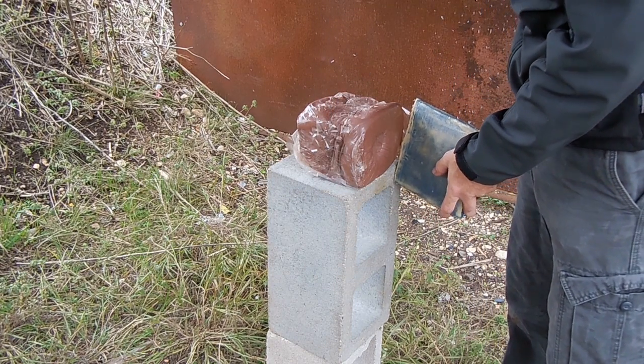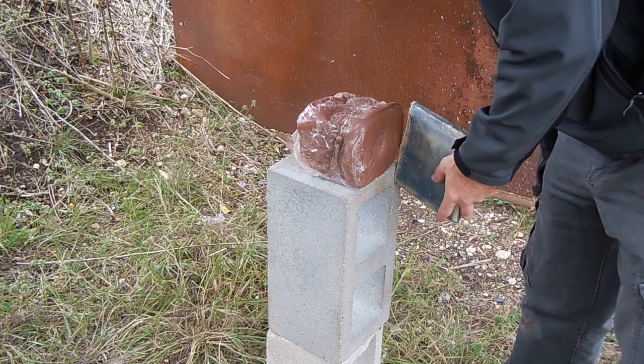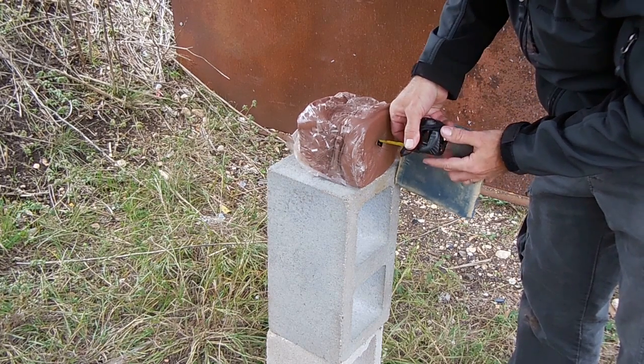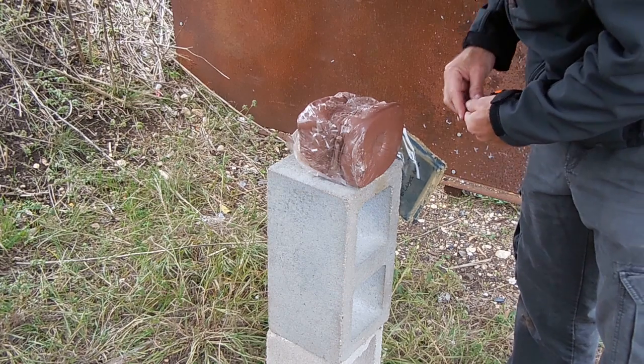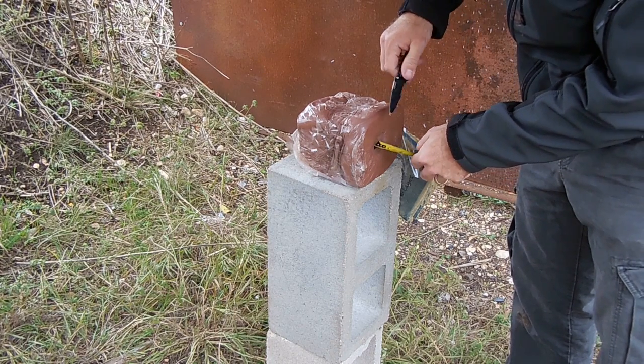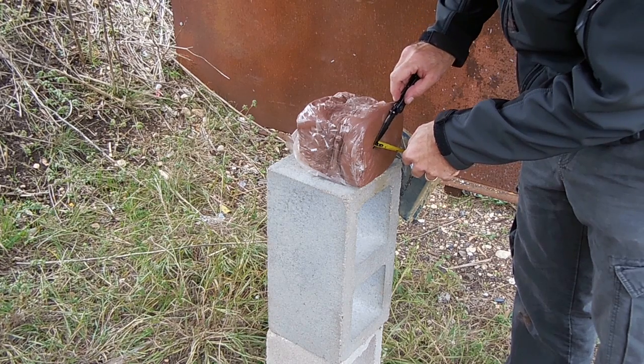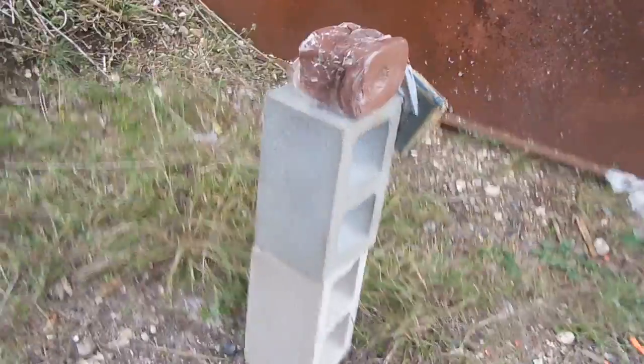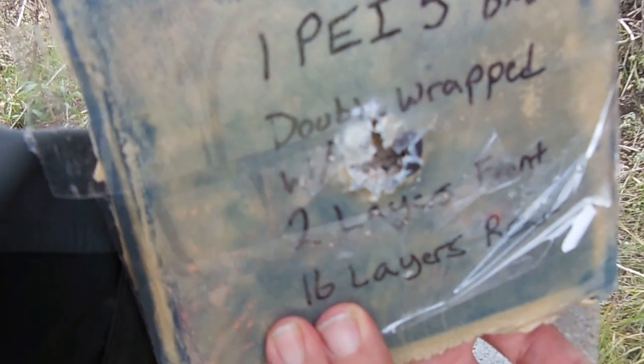There's no bulge on the back of this, and there is very little back face deformation. The depth here is minimal — we're looking at less than half an inch, about half an inch on that one. Look at the plate — no pass through, and it easily captured the round inside of there.